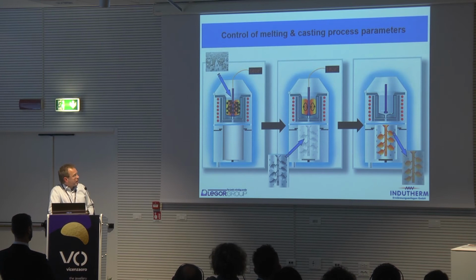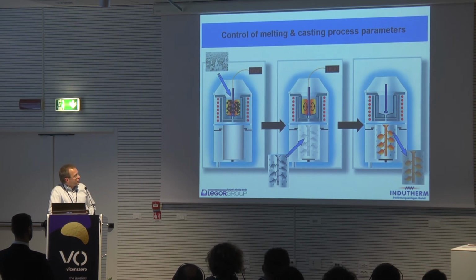We can differentiate between 3 different subsequent process steps in the casting process. First, the melting phase, then the pouring phase itself, where we have to load the flask at a certain point, and then after pouring, when the stopper rod has been lifted and the melt has poured into the mold, we have the cooling phase of the flask, and we have to take out the flask at a certain time. So just very quickly here, to focus on these 2 steps, which are sometimes not given enough importance.